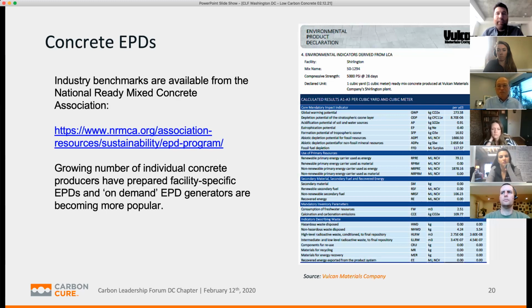And one thing to consider too is that when you talk about concrete, as I was saying, you can take those same sources and make 1,000 different mixes. One challenge for EPDs in this industry has been, how do I make EPDs for every mix that I have? It's very labor intensive, it's costly. And then if I make a decision like, oh, I'm going to change where I buy my aggregates from, or I change the cement that I use, I have to throw all that EPD out, right? It's not useful anymore because I've changed my source of supply.